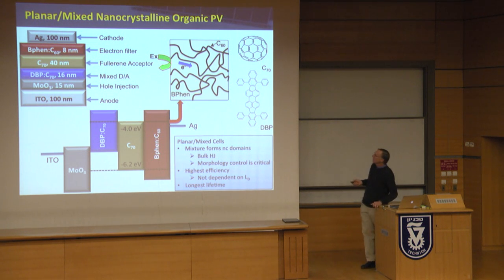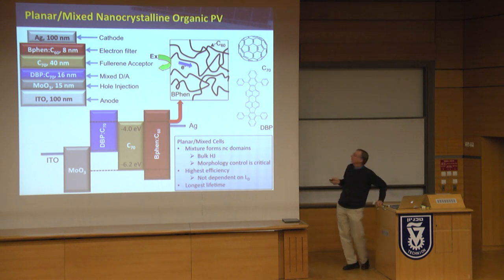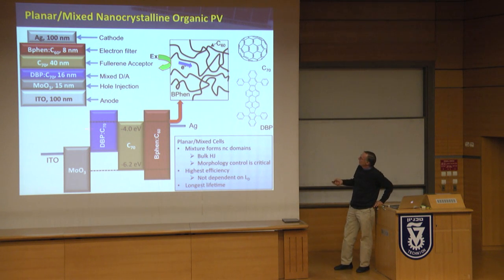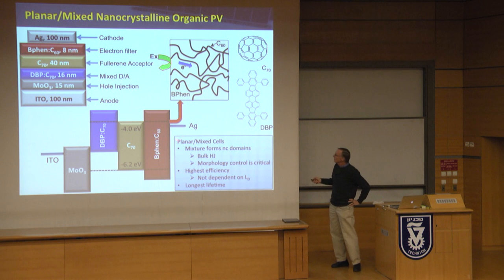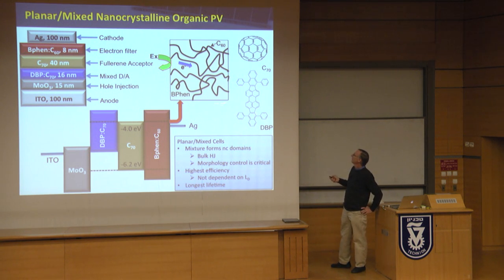And our best solution to this was to mix the fullerene C60 into a very wide band gap transparent material. And the C60 forms these little wires. And we call this an exciton filter, or an electron filter, because you have a small drift field across this thing. It's the built-in voltage. And electrons can find their way onto these wires, and because of the symmetry of C60, they form these chains, and it's quite conducting. But excitons are a little bit bigger, and they don't quite know what to do. They really can't transfer energy very effectively to the C60, and so they bounce off. And so this is a highly transparent, very highly conductive buffer.